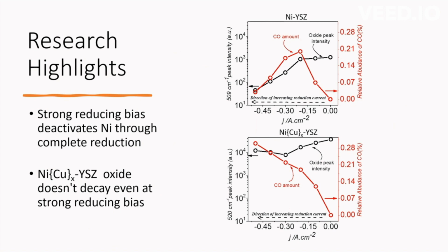We look into why the nickel YSZ breaks down while nickel copper does not. By Raman spectroscopy, we find that the oxide peak intensity of nickel oxide is maintained up to a current density of 0.2 amps. When we go beyond this current density, there is decay in the oxide signal. As we can see here, the CO production increases, the red one, up to 0.2 and then it starts to decay. So it coincides with the decay in the oxide peak, which means the oxide is required to carry out the